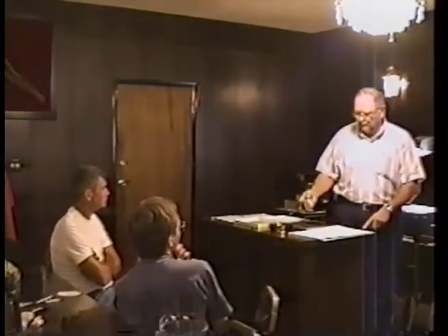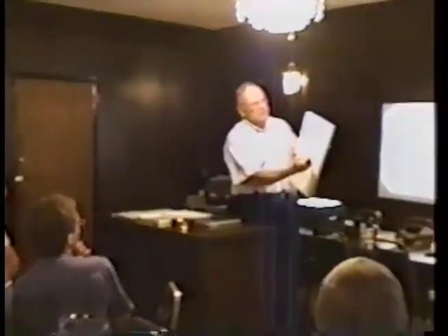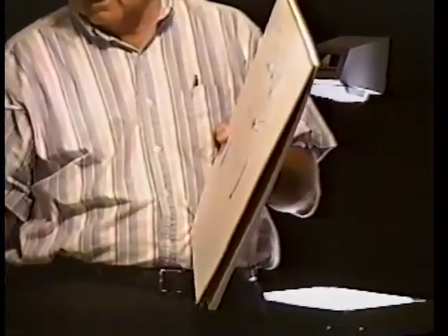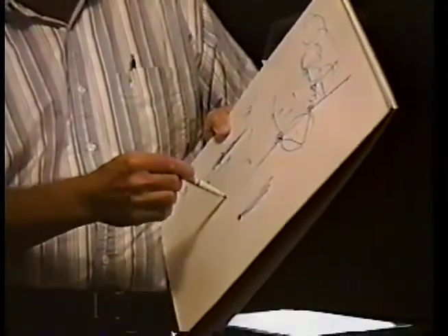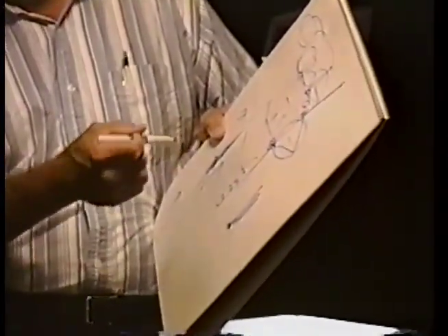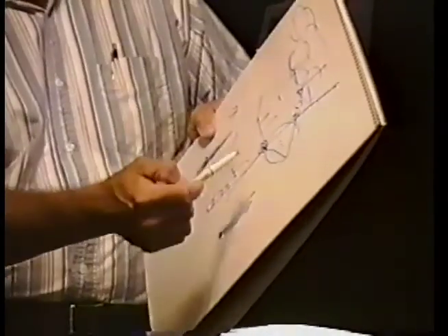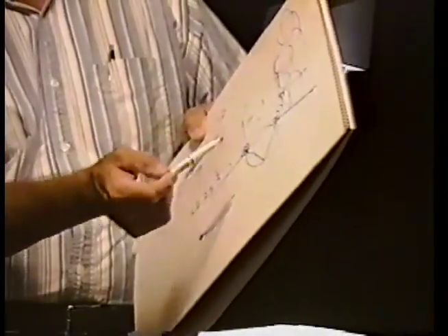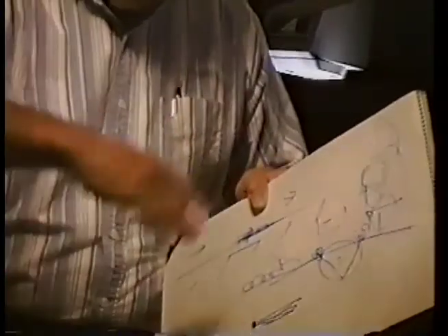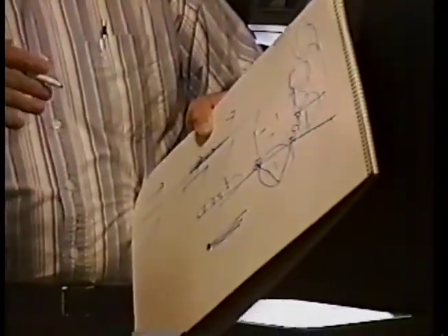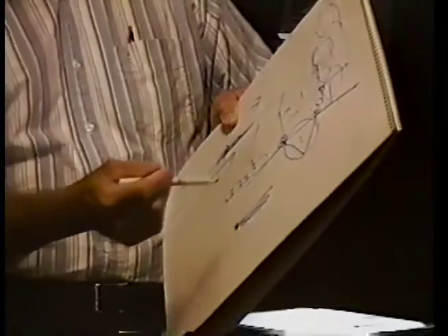One of the things that we do to control that, as well as prepare the surfaces, is we fine grit blast that bore surface before it's plated. And then our startup process is a reverse plate, which causes a scrubbing action to take place on that surface from the hydrogen gas. It scrubs itself clean of any debris left from the blasting process. And then they take a solvent and wipe out the bore for cleaning to get it degreased.